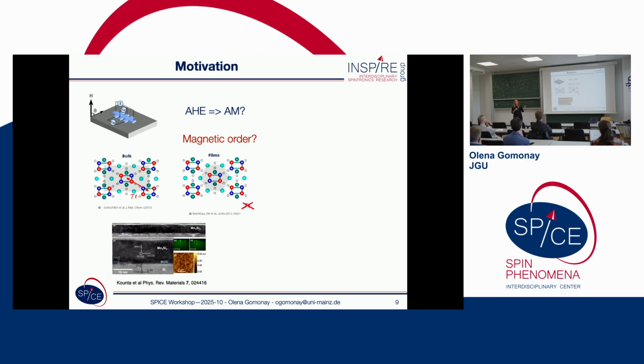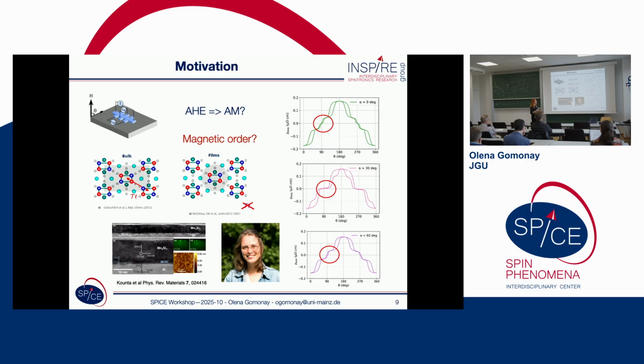And now I've switched to the problem of the magnetic structure of this material. The one feature which distinguishes antiferromagnet from altermagnet is the anomalous Hall effect, which in this case can be measured on the film with a Hall bar, which is oriented so that the hexagonal symmetry axis is perpendicular to the film. So if the material is antiferromagnetic, no Hall effect. If it's altermagnetic, there is a Hall effect. Nice and good.